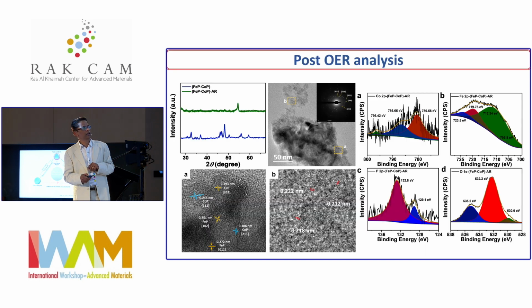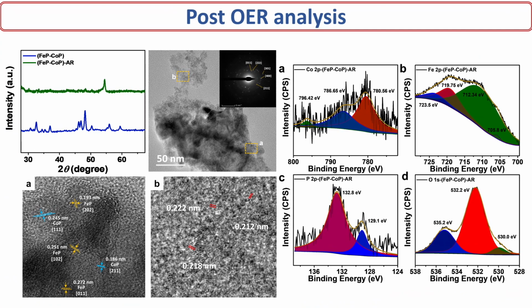We have looked into that, and after the post-OER analysis, we still find that there are crystallites of the order of 10-20 nanometer, and the formation of interfaces is still existing, but a little amorphization is also happening, increasing the porosity and so on. Even our XPS study indicates the formation of a metal-oxygen bond, indicating that there is some 10-20% oxide surface on the phosphide matrix.